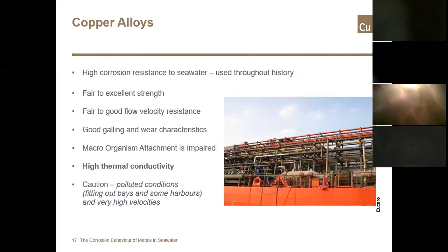So to consider the relative merits of the various copper-based alloys, it's necessary to understand their behaviour in more detail, and in particular under flowing conditions, when stressed and exposed to seawater. Another benefit of copper and copper-based alloys is the castability and weldability, and also the manufacturing, which can influence the choice of the alloy for a particular application. Other properties include anti-galling properties, and an impairment of the attachment of seagrasses, hard shells and shellfish. However, copper alloys can be subjected to higher corrosion rates when seawater contains ammonia and sulfides. So extended exposure to polluted conditions is probably not advisable for copper-based alloys.